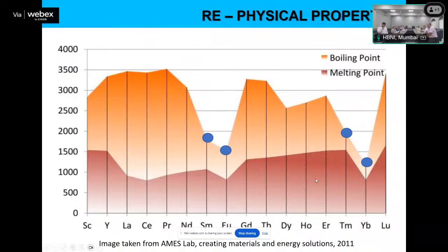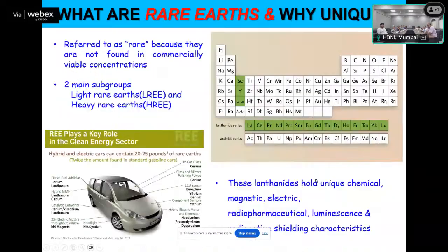And if you want to make, suppose, lanthanum, cerium, Pr, Nd, the method is basically fused salt electrolysis, like lanthanum chloride will be there in a fused salt, and at the cathode you will get lanthanum, at the anode you will get chlorine. We already had a plant at RETMP for lanthanum, cerium also, and Pr and Nd can be done. But another method for getting rare earth is to make their fluoride and treat with calcium and magnesium, which we had earlier in our plant. So NdF3 plus calcium gives Nd. This is the method, so that means only fluoride can be reduced to get this.